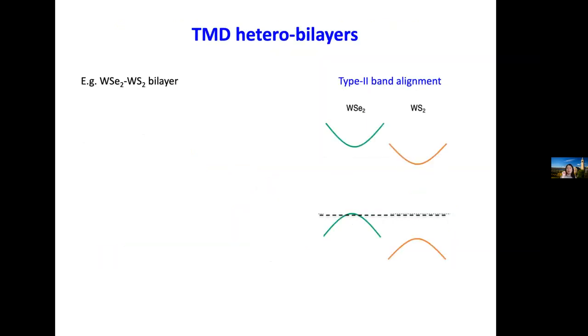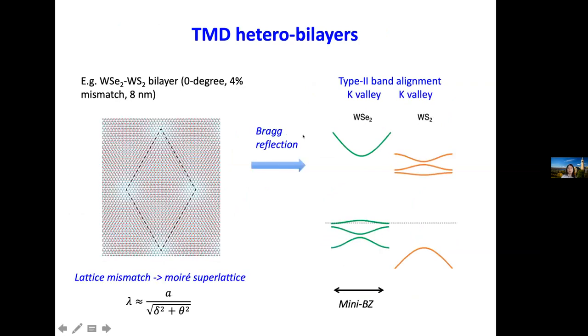So when you overlay two different TMD monolayers, in this case tungsten selenide and tungsten sulfide, they form vertical type 2 band alignment. So if you sweep the Fermi level, the hole will dope into tungsten selenide mostly, and then electron will dope into tungsten sulfide. So if the twisting angle is small between the two materials, so in the case of 0 degree, for example, because there is a large lattice mismatch between the two crystals, about 4%, you're going to get a lattice Moire period of 8 nanometer. And the Moire period is not very sensitive to the twisting angle because of a large lattice mismatch. So this gives us kind of a wider, if you would call it, magic angle.